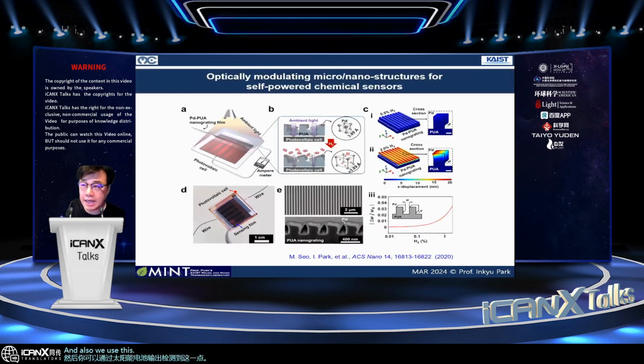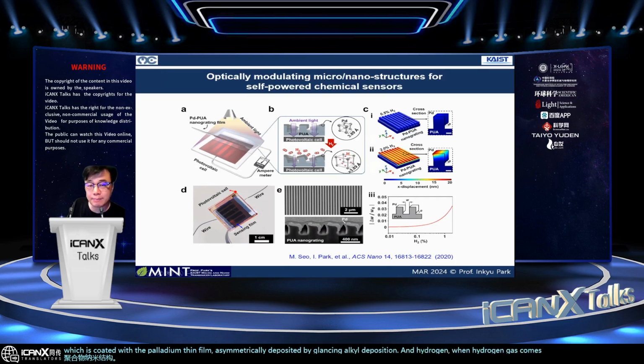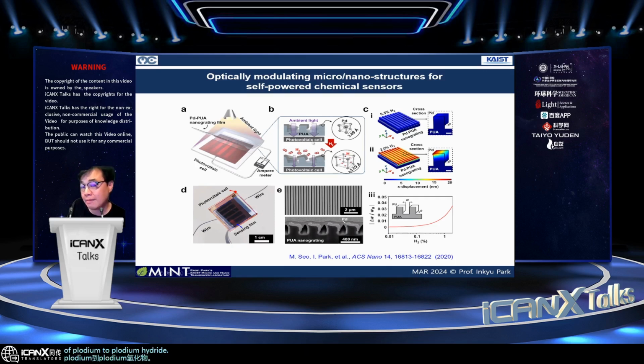And also we use this linear grating structure made of polymer nanoline structures, which is coated with a palladium thin film, asymmetrically deposited by glancing angle deposition. And when hydrogen gas comes in, you can see the expansion of palladium to palladium hydride. Then it tries to expand, but because of the underlying polymer structures, it will be bent, and then will block the light, which will be detected by the photovoltaic cell.